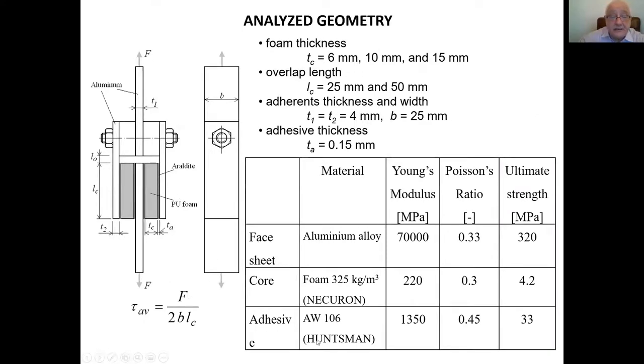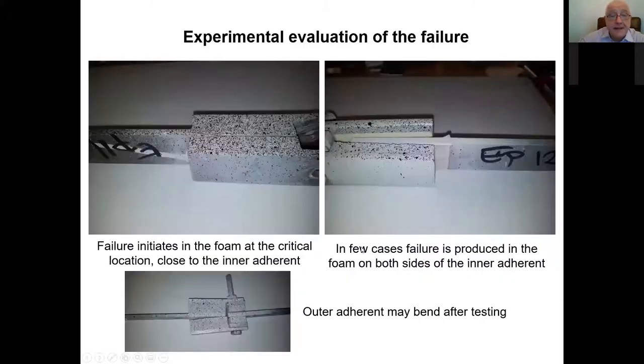So as I mentioned, we had adherents made from aluminum, foam, Necuron density 325, and Huntsman adhesive in between the adherents and the foam. So here are the dimensions. What may happen from the point of view of failure initiation, and this was what we were looking for using the DIC. Essentially, failure in most of the situations initiates in the foam, closer to the inner adherent. So this would be the crack which will initiate and propagate.